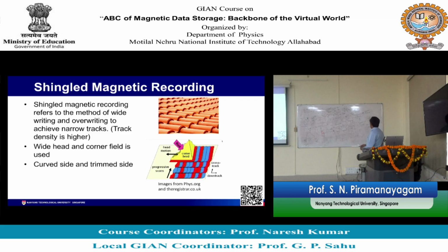So, what if we go further? Let us say your HK is like 1.5 Tesla and so on, we have been using, but there are materials like iron platinum, L10 iron platinum with HK of 7 Tesla. Okay, there are many materials like iron platinum, cobalt platinum with a very large anisotropy field. Okay. So, these materials have a very large Ku. That means, you can make the grains even smaller and we can achieve much higher densities than what we can achieve. Okay.